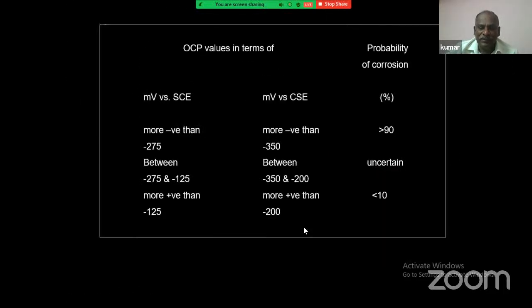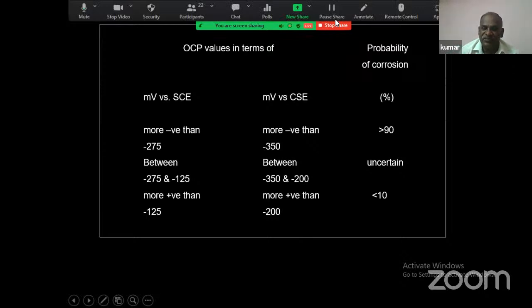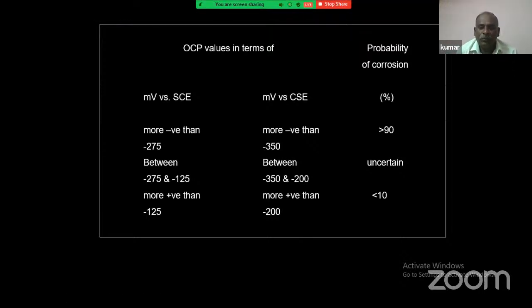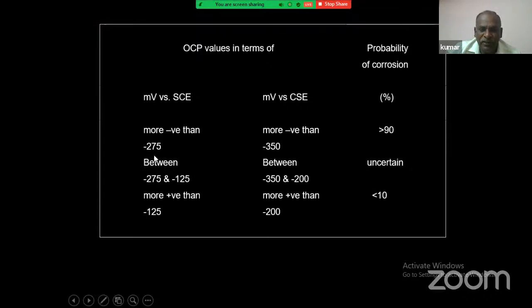So for example, ASTM C876 gives an idea about open circuit potential. With the open circuit potential, you can identify the probability of corrosion. For example, I have given this table with two types: one is versus the saturated calomel electrode, another is the copper sulfate electrode. In those measurements, if the saturated calomel electrode reading is more negative than minus 275, it leads to greater than 90% probability of corrosion. That means your structure is already corroded.